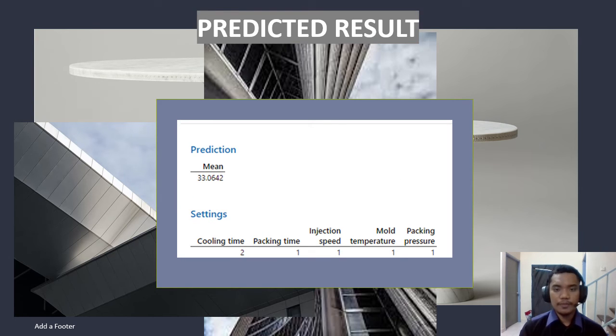And moving on to predicted result. Based on data analyzed, the optimum process parameter setting in the study are cooling time at level 2, packing time at level 1, injection speed at level 1, mold temperature at level 1, and packing pressure at level 1. It is shown that the predicted value of mean by using the predicted process parameter setting is 33.0642 megapascal, which resulted the highest value of ultimate tensile strength in this study. In this case, the ultimate tensile strength value for the condition setting is at its optimal value.